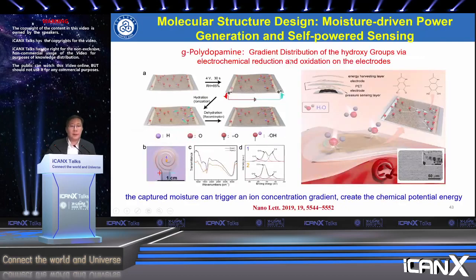And not only on the micro nanostructure designs, we can also make multifunctional sensors based on the molecular structure designs. For example, in this work, we developed a moisture-driven power generation and self-powered sensors based on polydopamine. We print the water-soluble polydopamine on the two electrodes, and through the electrochemical reduction and oxidation on the electrode, we can get the gradient distribution of the hydroxyl groups, so that it can capture the moisture.